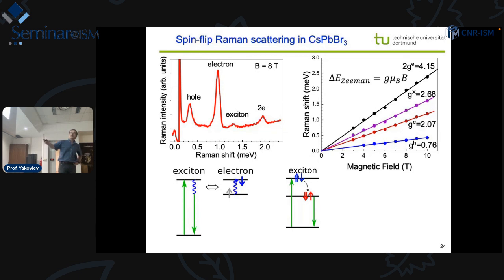So for the exciton process, this is a flip of the exciton as a whole, electron and hole flip the spin to the opposite, and this gives the Zeeman splitting. But for the electron spin flip, the process is like that. We have a resident electron in the crystal, we photo-generate an exciton, the electron flips its spin, and the exciton delivers energy for that. So in the scattering, the exciton is missing the electron spin, or for the hole it's the same.